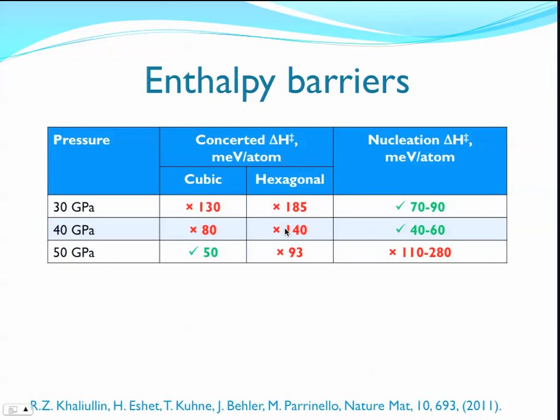And we can also compare energetics of nucleation versus concerted transformation, and we see that nucleation proceeds from much lower barriers at the experimentally used pressure, and at a little bit higher pressure, actually concerted transition becomes more favored.